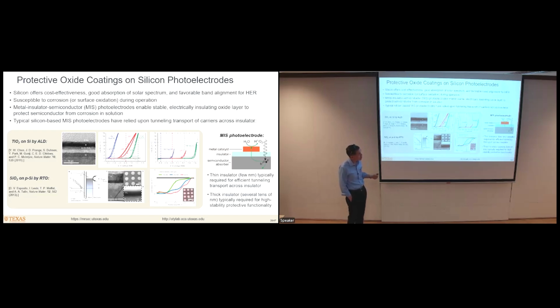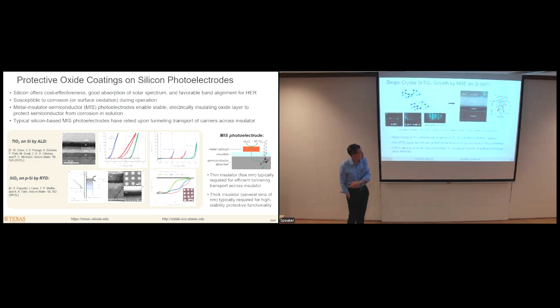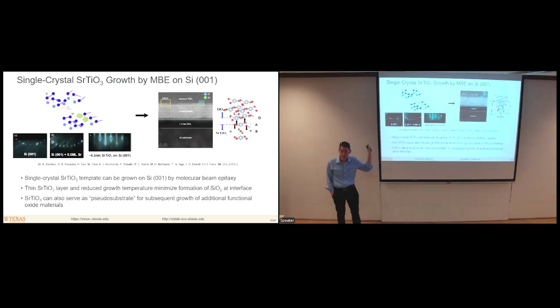So when we first started thinking about these kinds of problems, maybe roughly a decade ago now, the first thing that we thought about was, okay, well, are there materials that we can use that will serve as good protective layers, but that have favorable energy band alignments to allow for easy transport of at least one of electrons or holes, right, across this MIS structure? And it turns out that there is such a material, strontium titanate, okay, can be grown by molecular beam epitaxy in extremely high quality on silicon, okay?